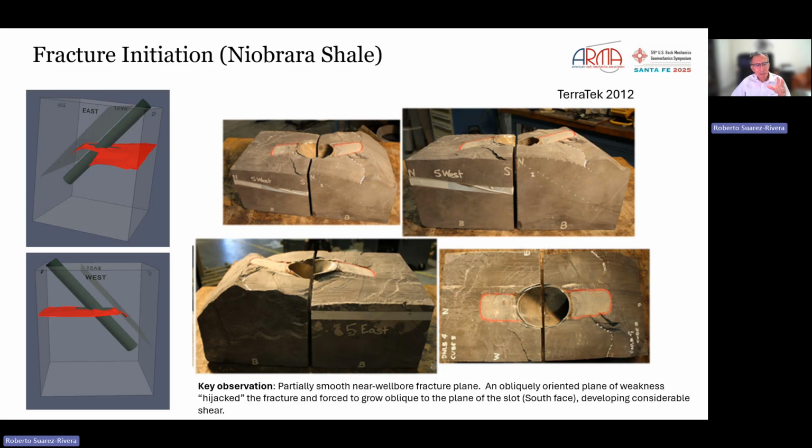And we do that with the CT scanning. And in order to be able to do that, what we do is we segment the large block into small little blocks, right? So we call them sugar cubing. So we sugar cube the large blocks. Every cube is about this size, and then it can fit into the CT scanning. It can scan it and provide a three-dimensional view of this block, and then digitally we reconstruct in order to go back to the upper scale.